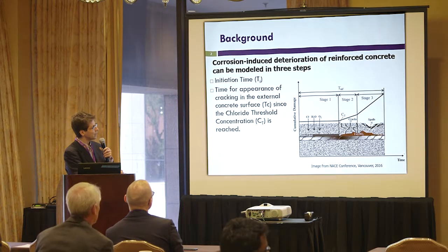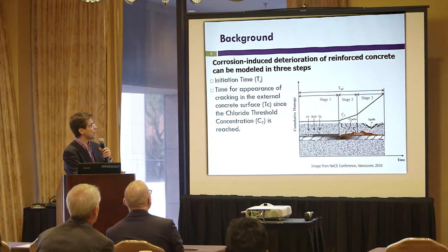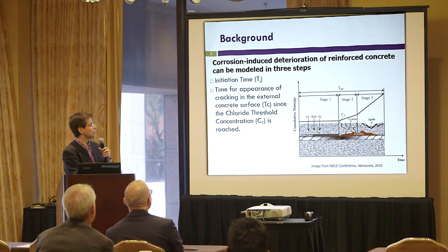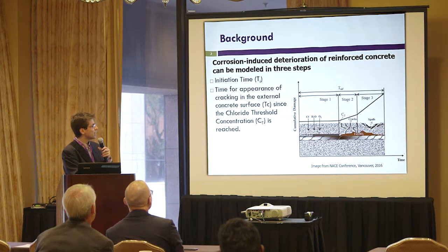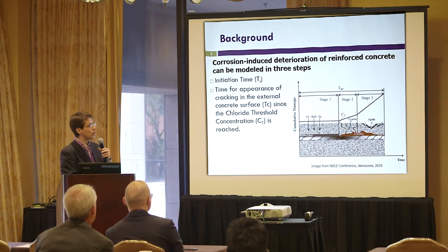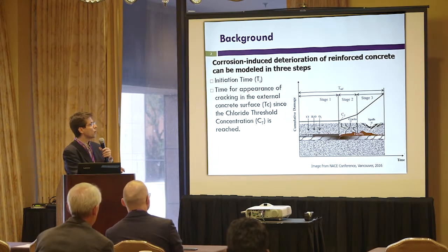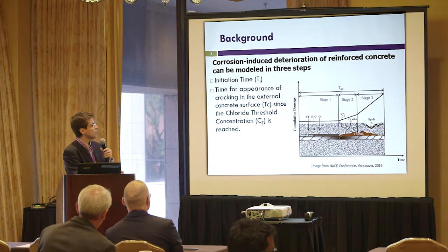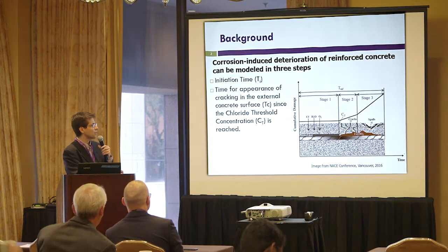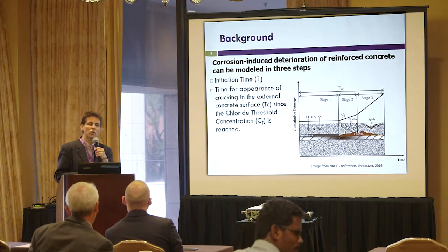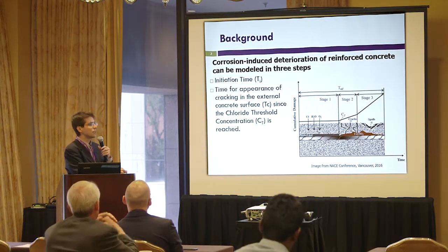It's where the electrolyte and the rebar meet, and of course if you put this in an environment, you form an electrochemical cell. This diagram illustrates the cumulative damage evolution of the rebar. The rebar is in a passive state — it forms an oxide layer that is stable and homogeneous. But once the corrosion precursors, which are water, oxygen, and chloride, migrate within the concrete structure, they will start to influence this passive layer and cause its breakdown.